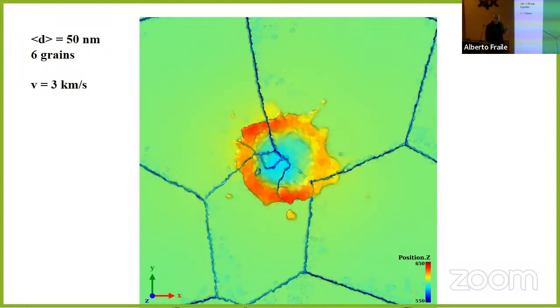When you have a single crystal, it's like butter. For example, if you have copper, with your finger you make a mark there. If you have a copper foil, it's not so easy to do that in tungsten. Tungsten is much harder than copper. I agree, but if you have a dislocation in a single crystal, it goes through. But if you already have these dislocations, it should work down much harder against any impact.